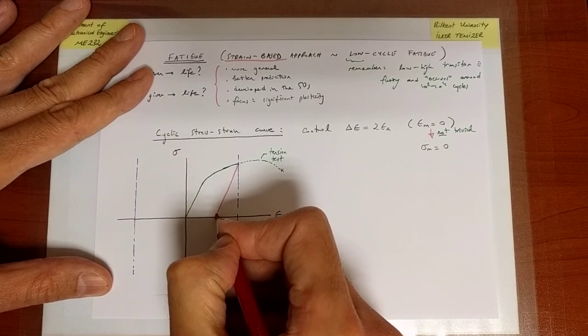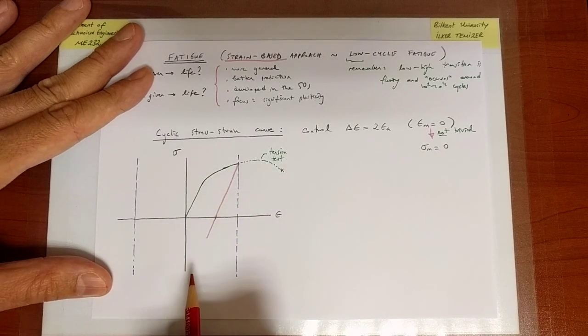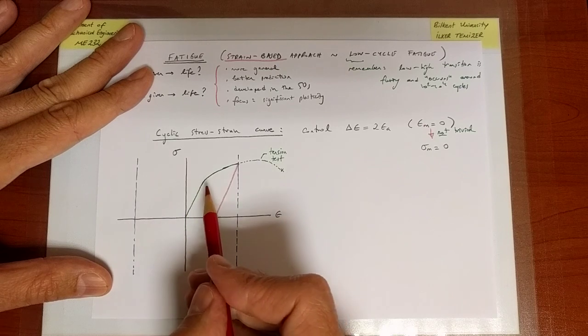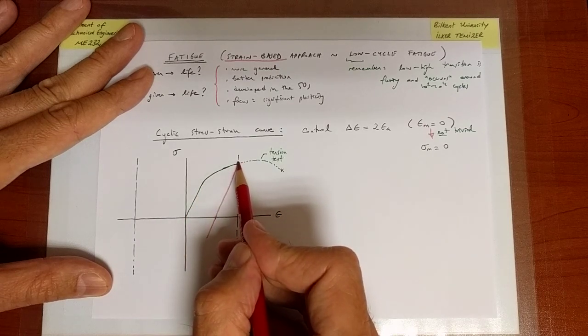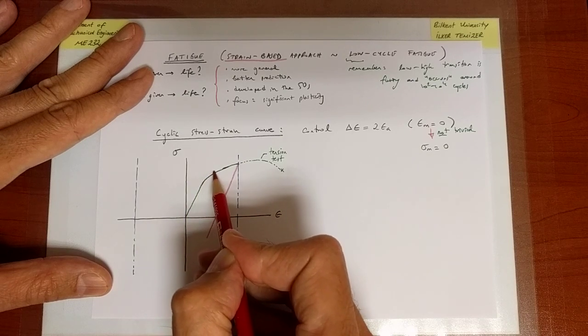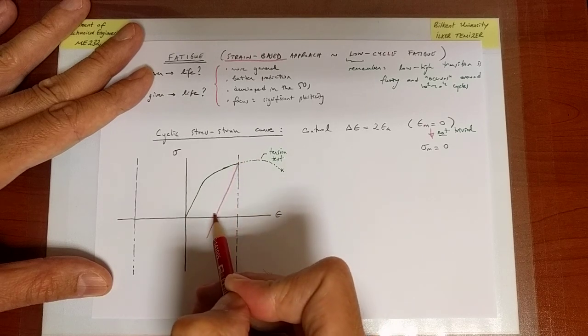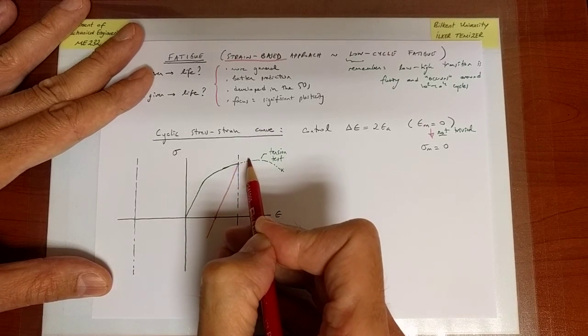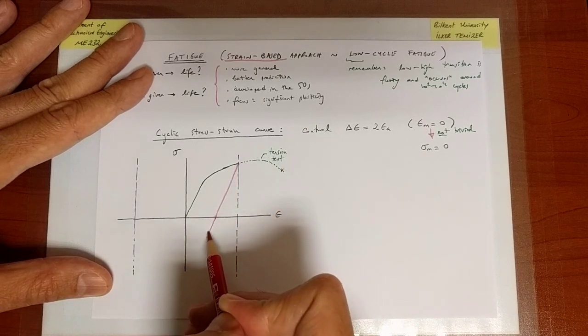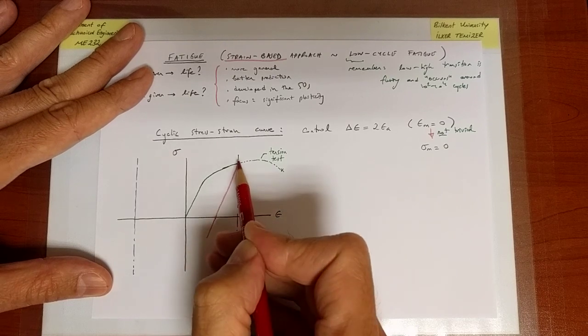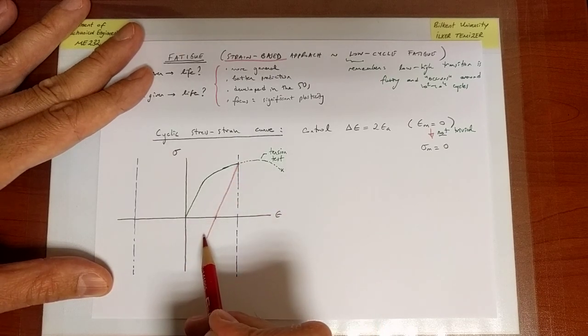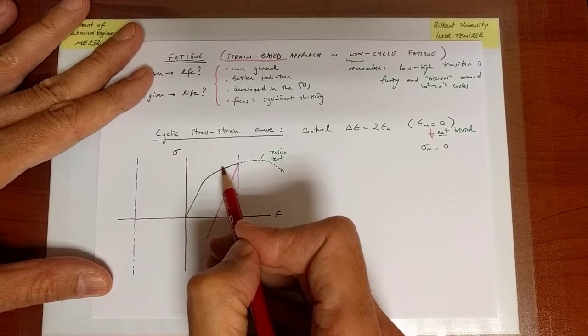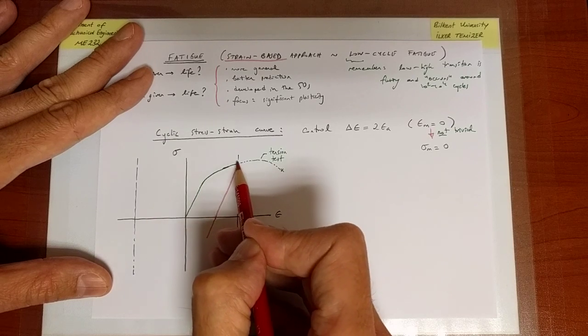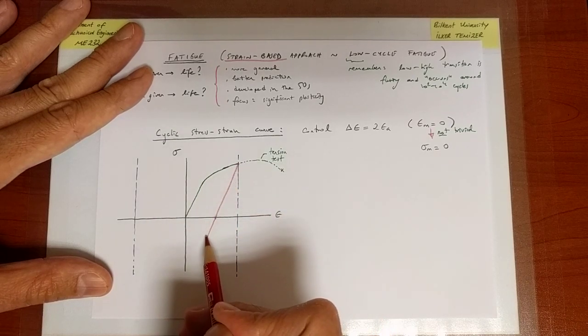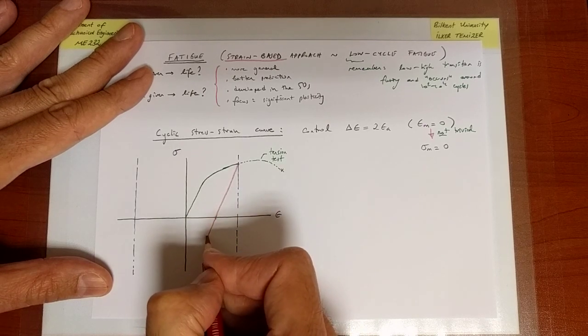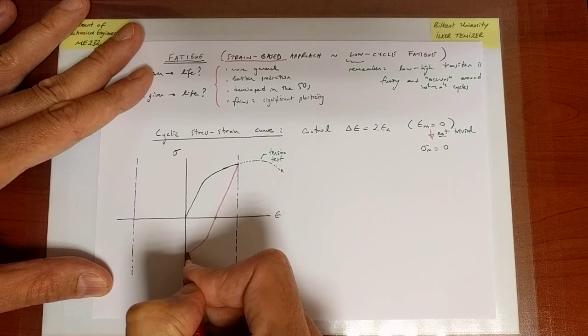What I'm going to do now is continue further. Something strange happens when we continue further due to the nature of the material behavior. We had yielded at this point, and the point of yielding continuously increases. In other words, if I had unloaded and loaded back to that point, we would get yielding at this stage and continue along the same curve. But when we load in the reverse direction towards compressive stresses, it turns out yielding does not occur at the same magnitude, but it can occur a lot earlier. This has to do with the hardening behavior that we discussed. If it hadn't hardened, it would go like this. But now it hardens, the strength of the material increases when we unload, but strength under compression appears to diminish and yielding occurs earlier. And then the curve goes like this.